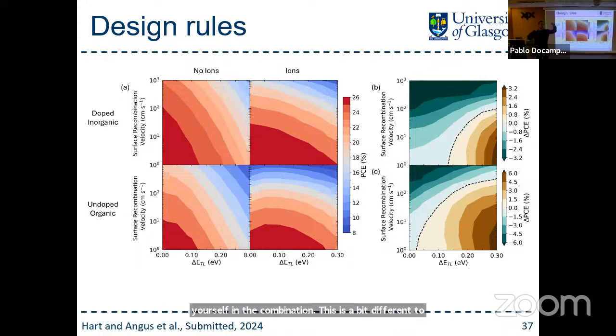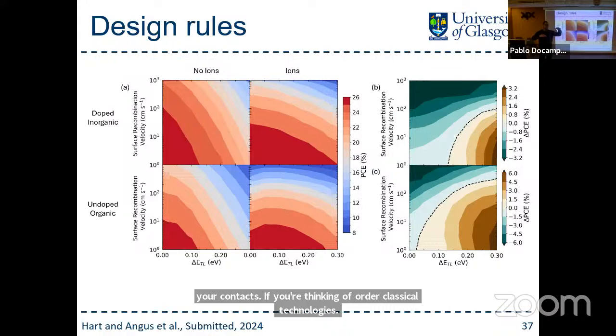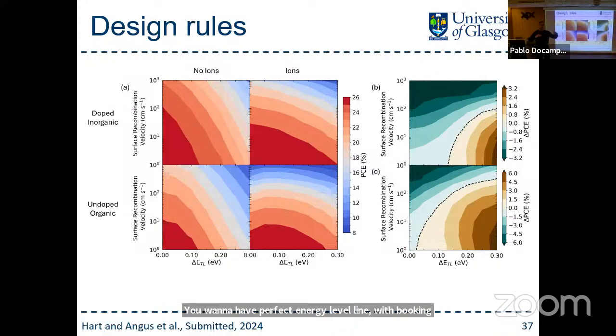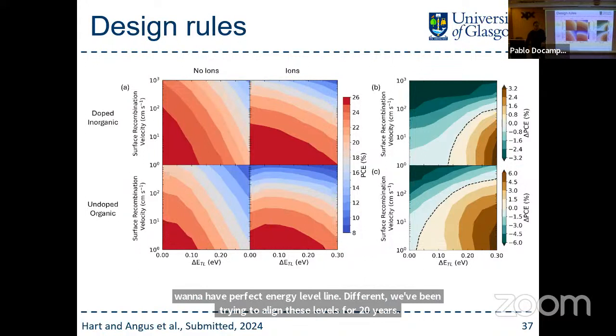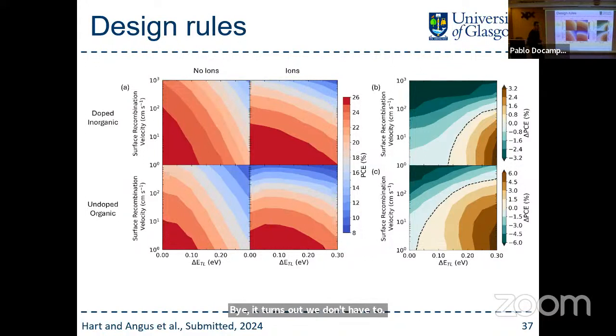This is a bit different to what you would do if you're doing organic solar cells. In organic solar cells, what you really want is perfect band alignment at your contacts. If you're thinking of other classical technologies, you want perfect energy level alignment. We've been trying to align these levels for 20 years. But it turns out we don't have to. What we need to be careful of is that we minimize the surface recombination. This is the outcome of this study. We can actually show that we're focusing on the wrong thing. We need to focus on minimizing surface recombination.